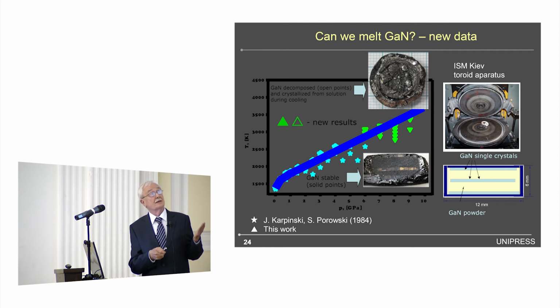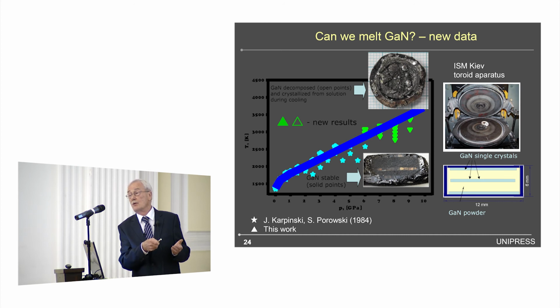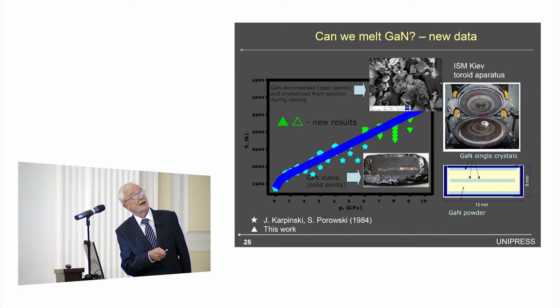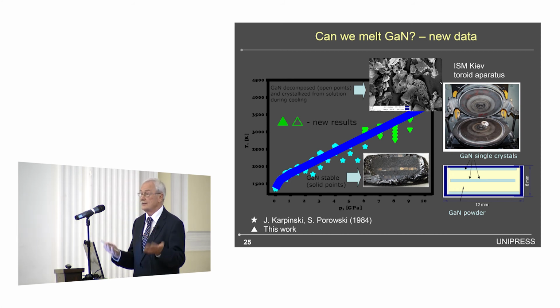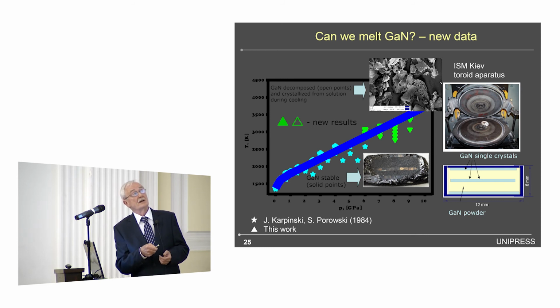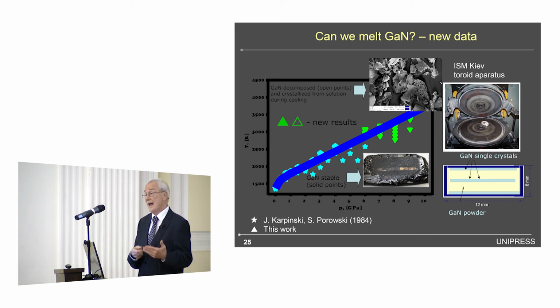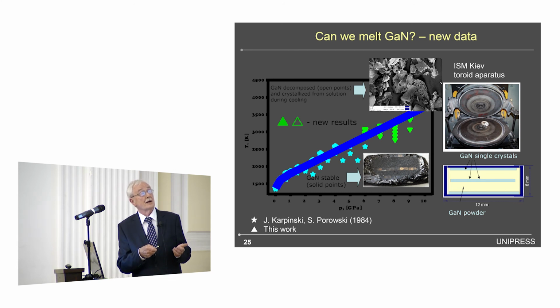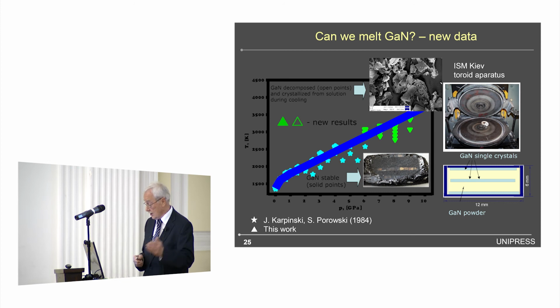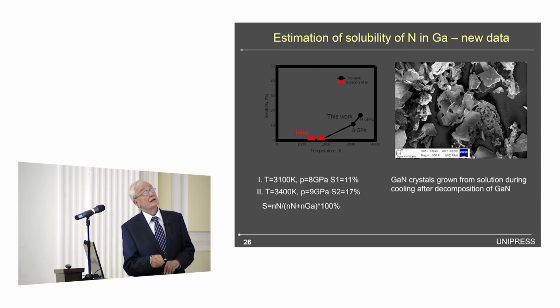And what was extremely interesting was that if we etched these samples, which are completely decomposed, we got a result showing newly grown crystals which existed inside gallium. They were crystals grown from a solution of nitrogen in gallium during cooling of the system. So measuring the weight of these crystals and comparing it with the weight of the whole sample, we were able to measure solubility of nitrogen at the conditions of the experiment. And this is shown here.